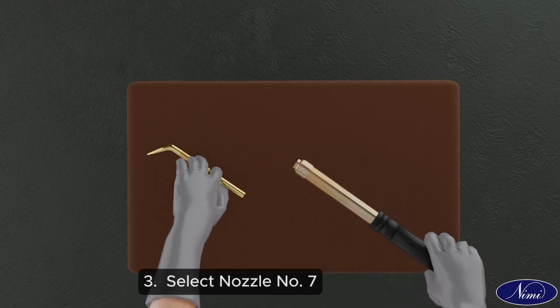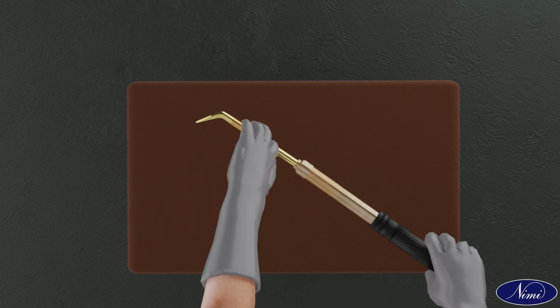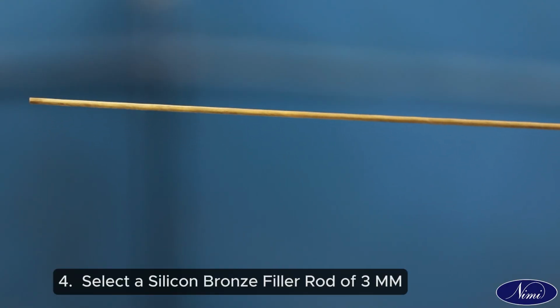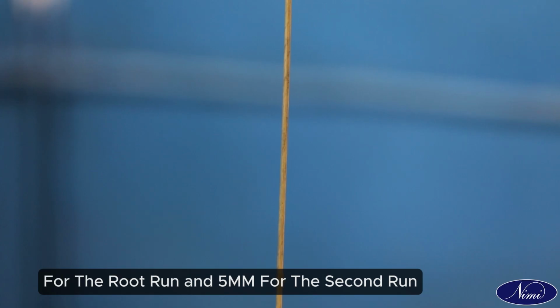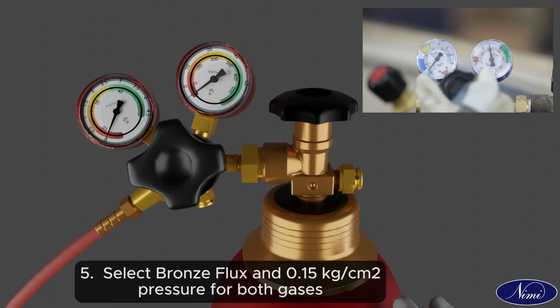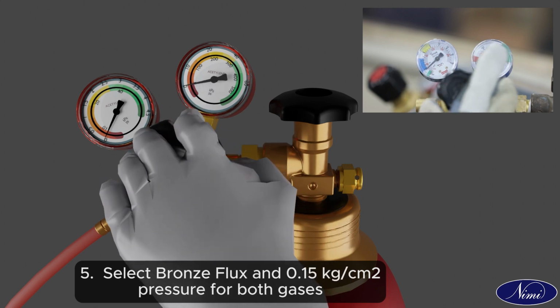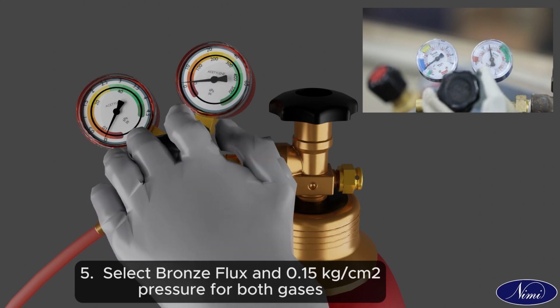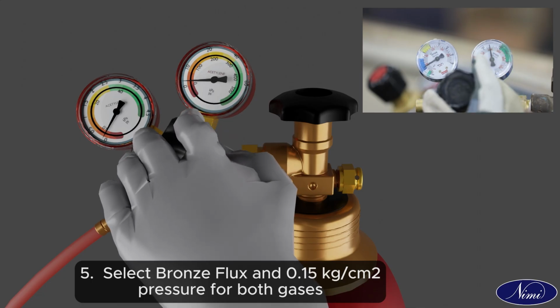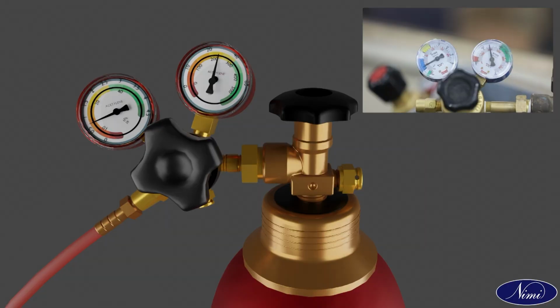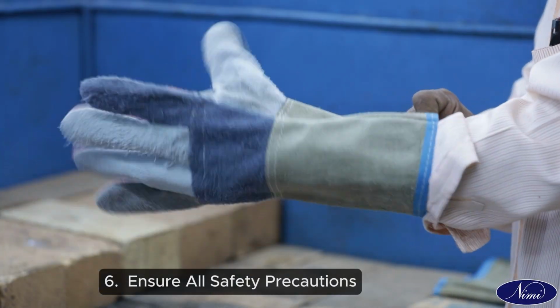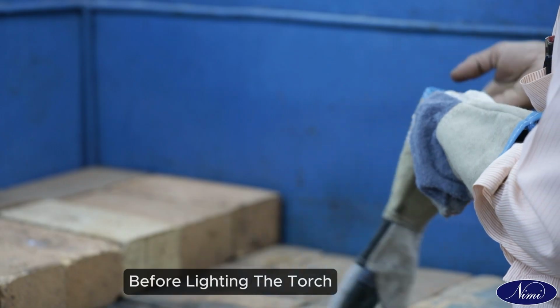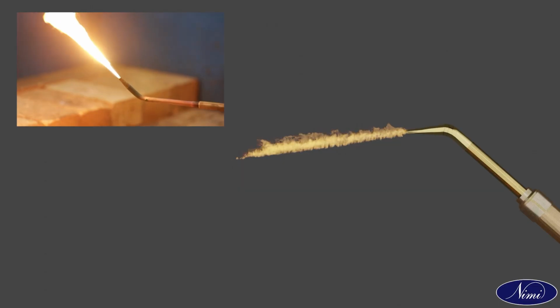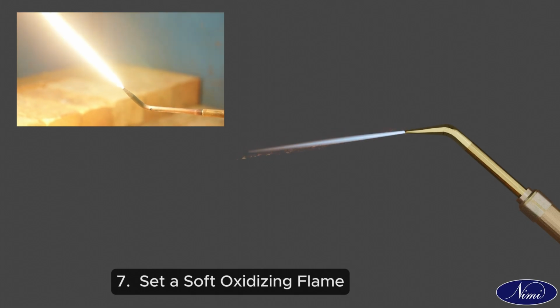3. Select nozzle number 7. 4. Select a silicon bronze filler rod of 3 mm for the root run and 5 mm for the second run. 5. Select bronze flux and 0.15 kg per centimeter square pressure for both gases. 6. Ensure all safety precautions before lighting the torch. 7. Set a soft oxidizing flame.